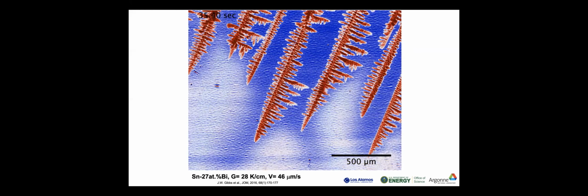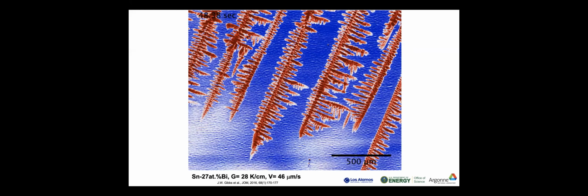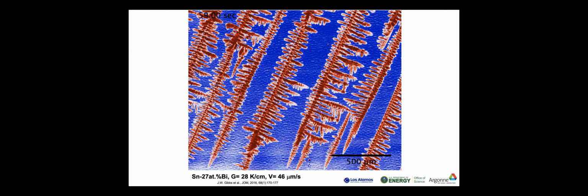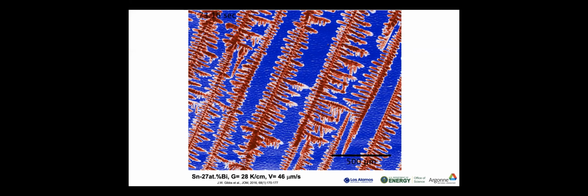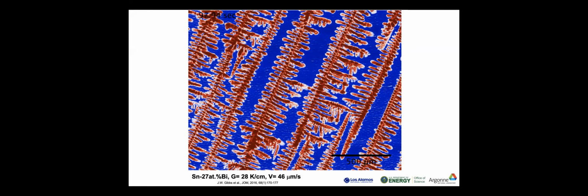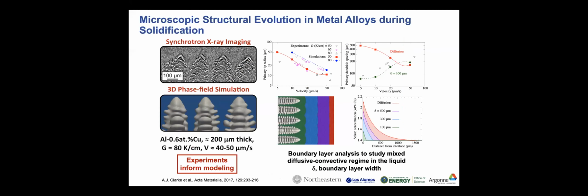So here we can see the tin-rich dendrites sweeping into the field of view. We then see the bismuth solute falling in plumes. Again, the bismuth solute is higher density, and we see this enhanced effect of gravity. So why is this important? It's important because if I take this information to a modeler, convection is something that's not typically considered in modeling.